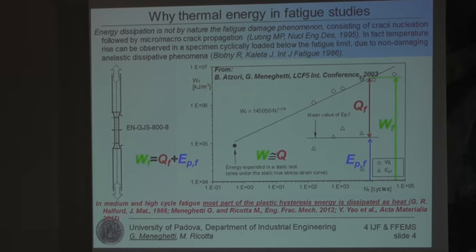This means that if we want to measure the energy stored inside the material as a difference between the total mechanical energy expended and that released as heat, our measurement will be affected by great uncertainties, because we have a very big quantity, we subtract a quantity which is of the same order of magnitude, so the result of our calculations will be affected by great uncertainties. So that is why we proposed to use the energy dissipated as heat as a fatigue damage indicator.